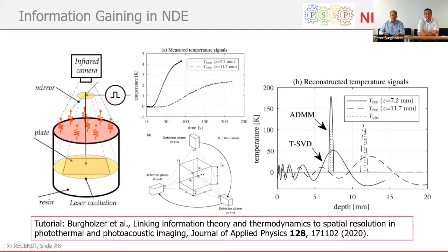So with that, I just will give you a last picture here, that you can do it not only from one side, but you can do it from several sides. And this is called photothermal tomography, because you can use the photothermal technique from that side, and from that side, and you can combine these results, and this helps you to really reconstruct what's inside, also at a higher depth.